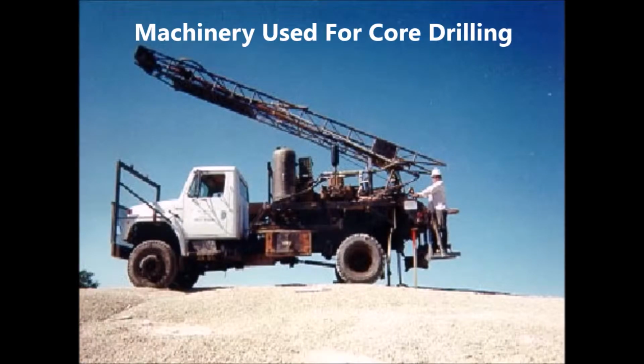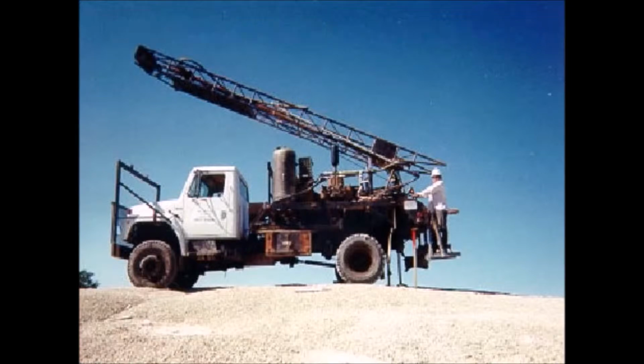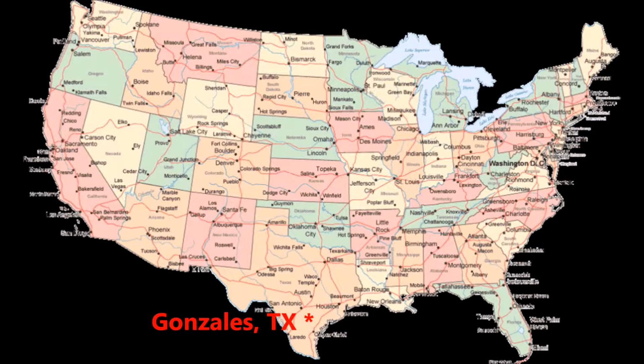We will drill on 50-foot centers, selecting cores from the ground. With those cores, we will do specific tests to make sure it is consistent with previous clays that we have mined for MycoAd products. The tests we do are things such as HPLC, which will be the first indicator as to whether or not the clay has mycotoxin binding characteristics. We also do cation exchange capacity, which measures the ionic content of the clays. We also measure calcium magnesium levels, and we do XRD, which is X-ray diffraction, in order to measure the exact mineral content of the clays.